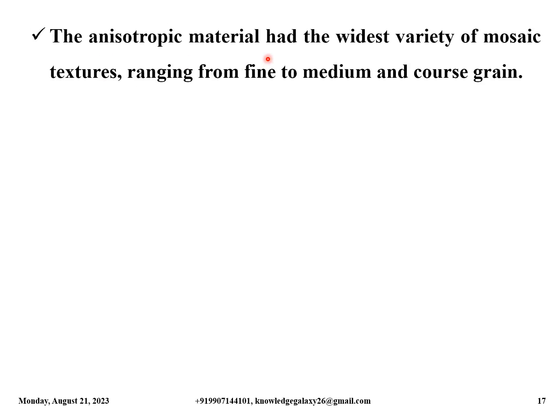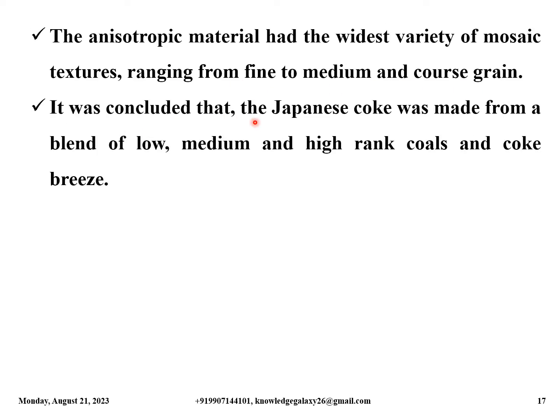The anisotropic material had the widest variety of mosaic textures ranging from fine to medium and coarse grain. It was concluded that the Japanese coke was made from a blend of low, medium and high rank coals and coke breeze.